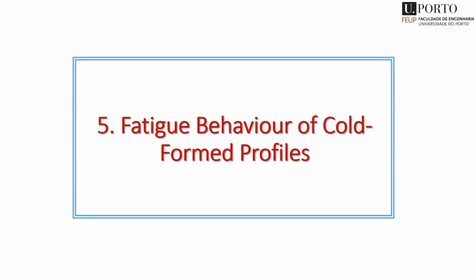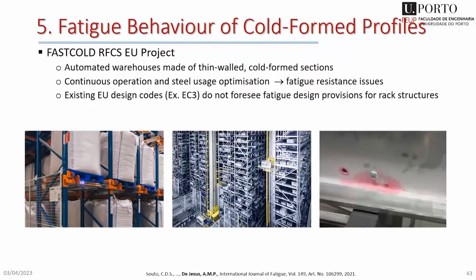Okay, finally, I would like to refer just a few seconds about cold-formed profiles. As I told you, these kinds of structures, the rack structures, are used for e-commerce, and nowadays they are running 24 hours, 7 days. Loads are increasing, speeds are increasing, and design restrictions are pushing to thickness reduction. And we are starting to observe critical failures in this equipment. And we realize that there are no design rules in our European Eurocodes for these thin profiles, because the European codes were prepared for thick sections.